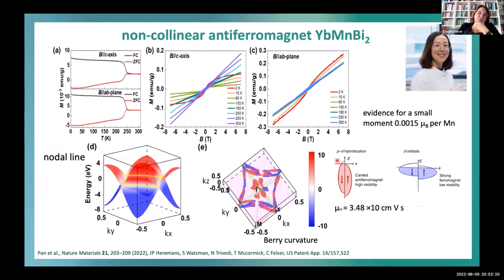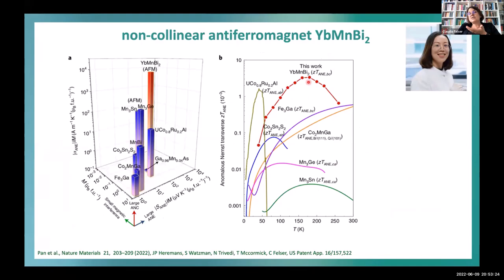So this was the reason for her to make the material, to measure the material, and indeed it shows an even larger Nernst effect than, for example, manganese rhodium germanium, and even the ferromagnet. So this is an antiferromagnet with a really giant Nernst effect. So we are reaching now values which are coming close to application. And this is simply by accidentally stumbling somewhere, taking a magnetic material. Oh yeah, maybe it's non-collinear, and measuring something.